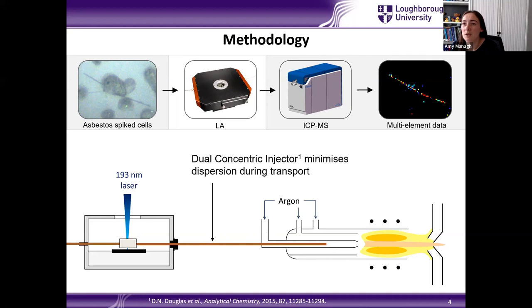In doing so, we're able to get a much faster signal response as well as higher sensitivity. And as well as this design here, the DCI, there's been a lot of work by other universities as well. The net result of that is that maybe 10 years ago, it would be about a second for your material to pass from your laser ablation chamber into your plasma. Now there's many, many different groups that are reporting peak washouts of around 1 to 2 milliseconds. So there's been a dramatic development of the interface between the laser ablation and the ICP.